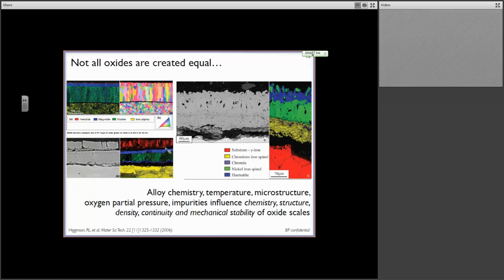If we look at these, and in fairness, these are both steels as well. This one over here is a low carbon steel, and this one over here is at least a low stainless steel, and they both have been oxidized at very high temperatures. So this is quite extreme. It's not fair. They wouldn't really be used in service, but they're good examples. In the case over here, this is actually what the scale looks like. So the steel alloy is down here, and all of this is oxide scale.